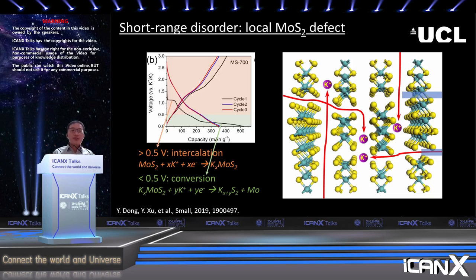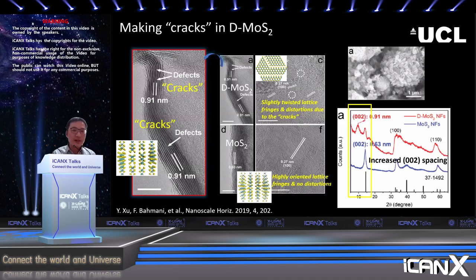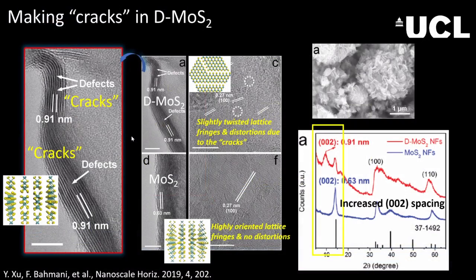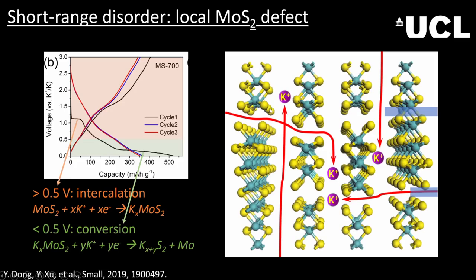So we use a very simple hydrothermal synthesis. I have just realized that a lot of the synthesis I have done over the years are actually quite easy, quite scalable. So what we did here is we changed the precursor amount of thiourea, which is the precursor of sulfur in this reaction. When we increase the amount of sulfur precursor, we can actually make cracks in the layers, which mimics the defects I explained in this slide.